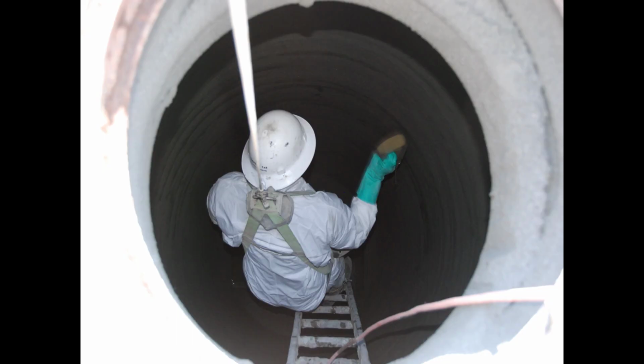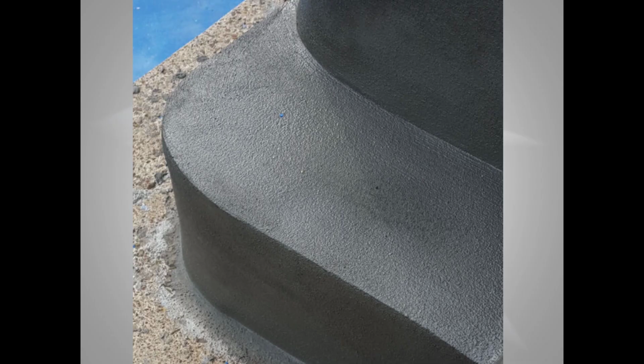Here you see a worker who's entered the manhole, and he's got a sponge in his hand. When you centrifugally apply the mortar, typically all you have to do is just sponge it. If you apply it with a nozzle, typically you would knock it down with a trowel first and then sponge it. And after this step, you have a very unique situation.